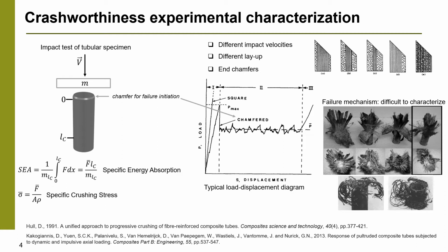A typical load displacement diagram is presented on the right, so you can estimate the importance of the end chamfer of the specimen. In case of a flat square end without chamfer, the response of the specimen is very stiff, and failure may occur far from the contact with the mass, so the crushing process is not appropriate. The main parameters which we can vary are impact velocities, layup, and chamfer geometry. Failure mechanism is difficult to characterize, as you can see in these pictures, but some key patterns can be detected, such as propagation of cracks, fiber deployment, or crushing to debris of small pieces.